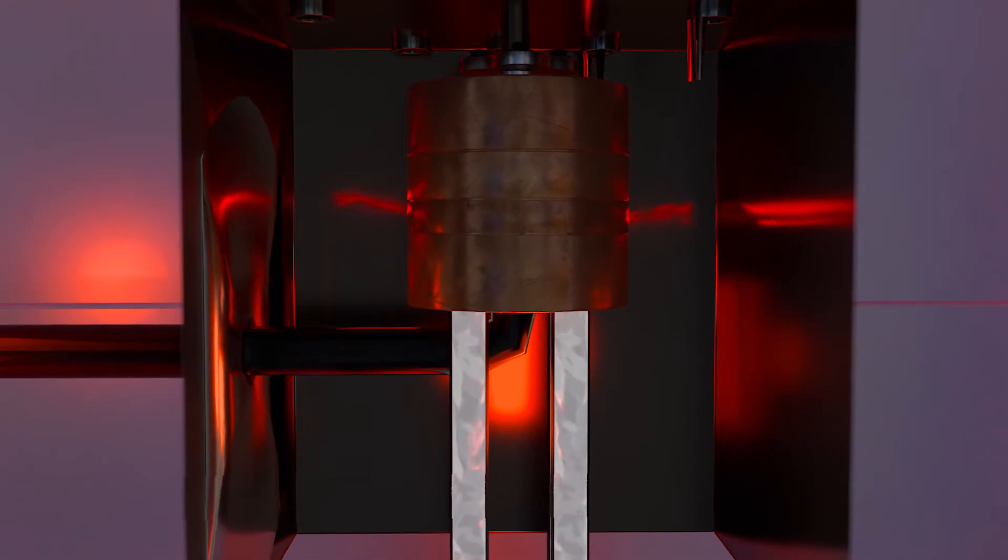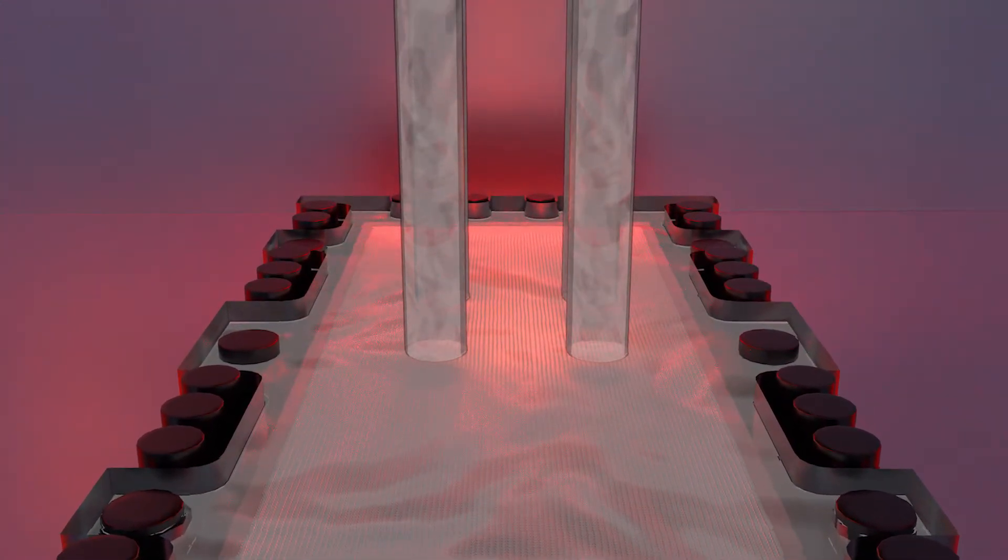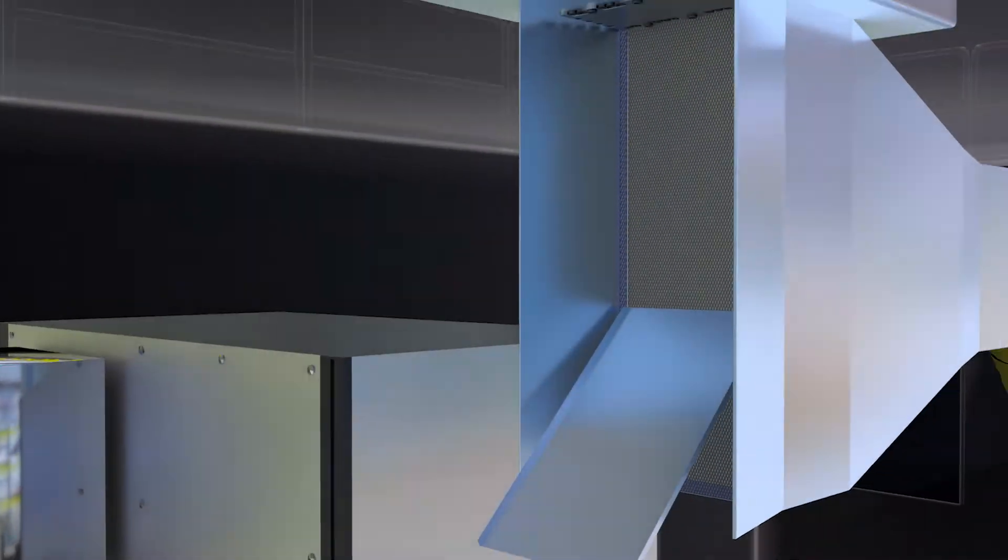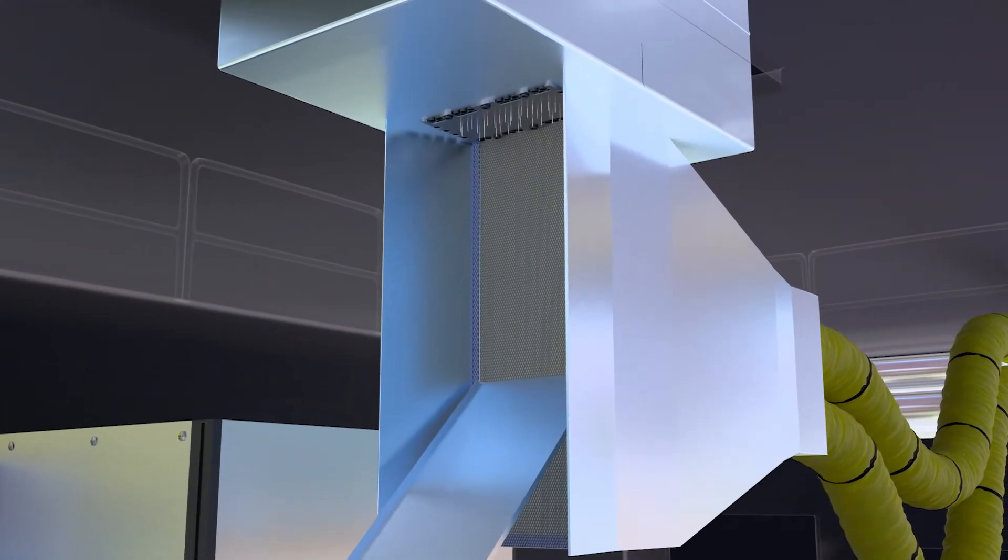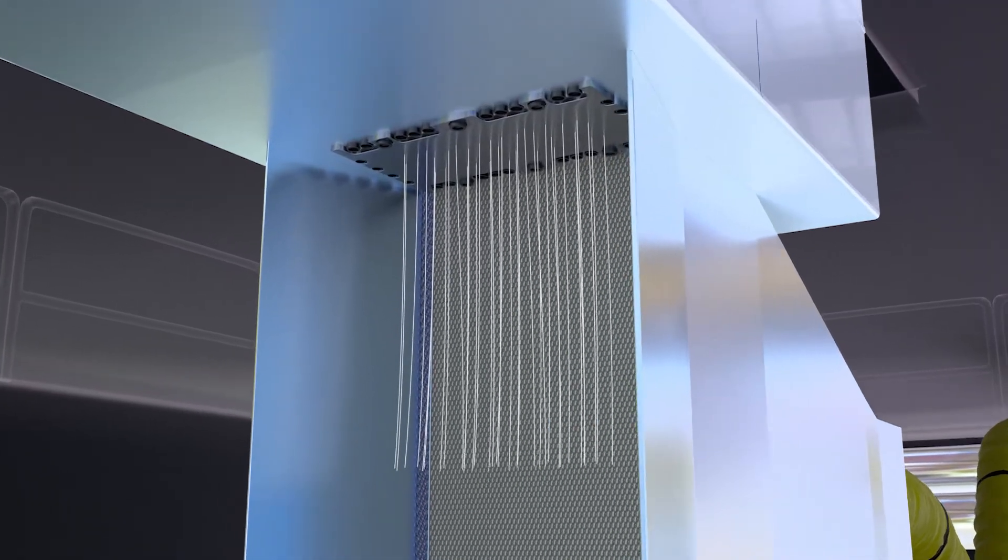The melted polyethylene moves through a filtration system to remove solid particles such as dirt or sand. The melted plastic is then pushed through a spinneret, a plate with hundreds of passageways determining the number of filaments per strand.